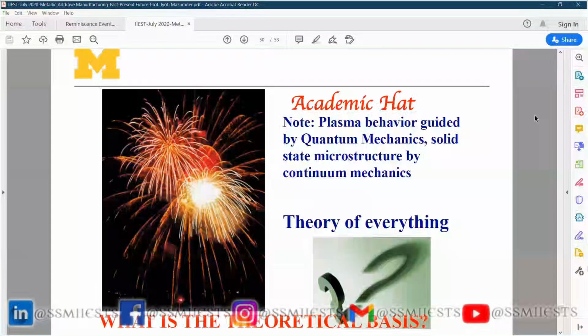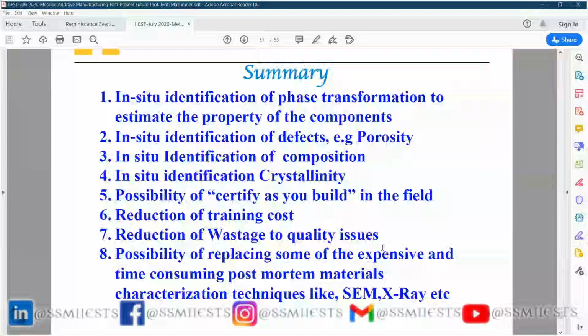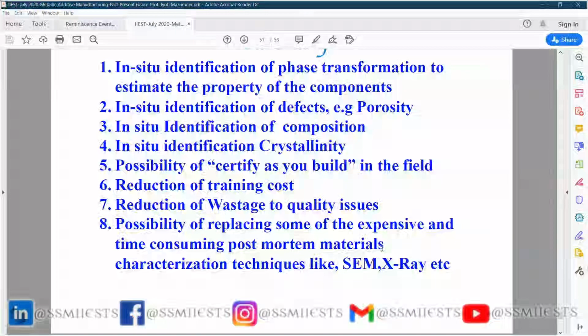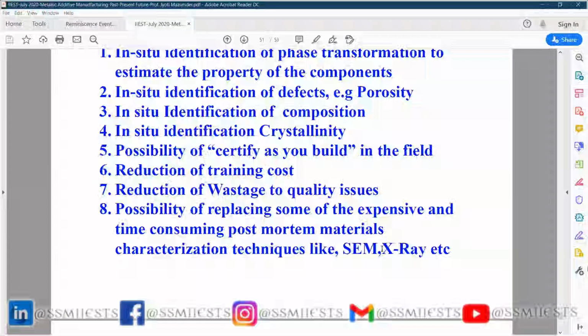So with that, my summary is we can do the in situ identification of the phase transformation, in situ identification of the defect, in situ identification of the composition, in situ identification of the crystallinity. So it's possible to certify as you build. You can reduce the wastage and quality issues, and possibly replace some of the expensive and time-consuming post-mortem material analysis like SEM, X-ray, etc.